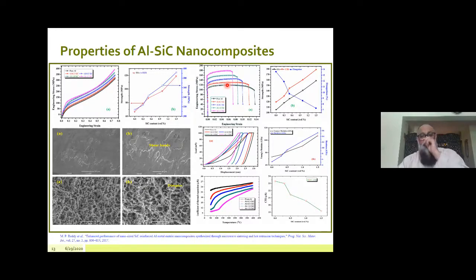And this is the tensile testing of the developed aluminum silicon carbide nanocomposites. We can see that the strength of aluminum is increasing, whereas the elongation is reduced because we are adding a brittle phase. Silicon carbide is a brittle phase in the ductile matrix, which is aluminium. We have summarized the calculated values of yield strength, ultimate tensile strength, and elongation. We can see that the yield strength and the ultimate tensile strength increase, whereas the elongation decreases.